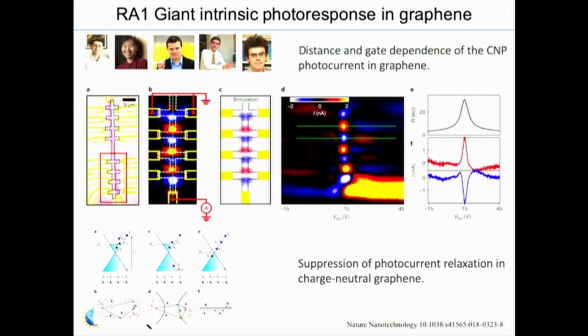And there's another one which is kind of surprising, a recent publication, that if you have really clean graphene, you see an entirely new type of behavior. And imagine that you have a regular material, and if you shine a photon on it, the photon will create an electron-hole pair, and suppose it's a super clean material, they'll just then move away from it in opposite directions. But in a clean material, it will go in any direction that you want, and so there's no current, because some are going right, some are going left, and so on and so forth. And that's normally what you see in graphene, too. But if you go to this magic point, this is a picture of the two crossed lines, a picture of the energy versus the momentum for graphene, the two actually cross at what's called the Dirac point.